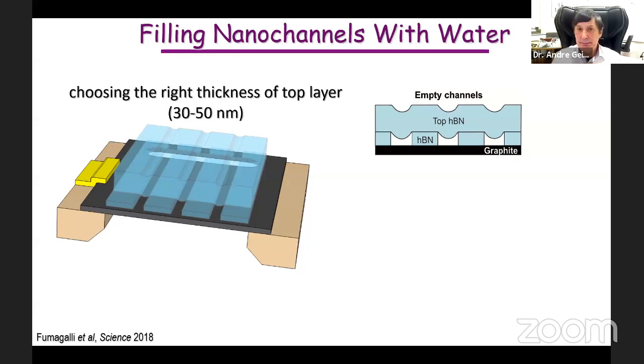To study this something else, and we continue this work intensively, it is important to make absolutely sure that water is inside those capillaries. To make sure, we specially choose the top crystal, not very thick, but kind of thinnish. Then the interaction of the top crystal with the side walls makes the top crystal sag a little bit into the capillaries, like schematically shown here. Because it sags inside, we see that the capillaries are empty, say in vacuum.